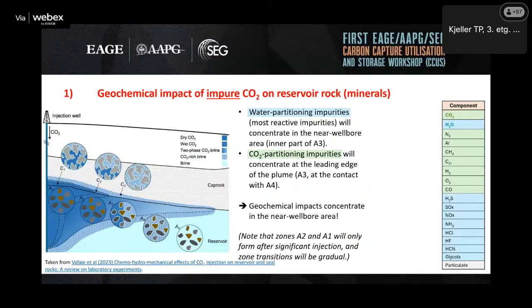Regarding that impact, we can identify two or three main chemical impacts. On the one hand, we have impurities that increase dissolution, so as I said, acid forming, etc. On the other hand, we'll have impurities that increase precipitation. Taking the example of a carbonate reservoir, if you introduce SOx, that forms sulfuric acid, which then reacts to form gypsum or anhydrite, which may have a larger volume than the calcite it's replacing.